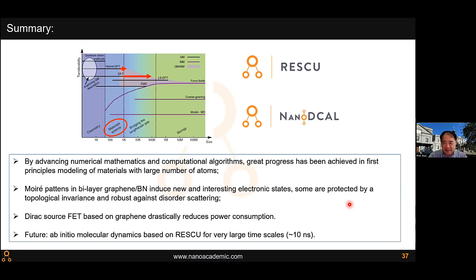But for interconnect, for many years I worked with SRC, Semiconductor Research Corporation, on interconnect. These are interconnect wires, and that's a very major problem for metal wires. Intel actually changed their process recently from copper. Many years ago, it was aluminum. What I worked on are copper nanowires. When these wires go down to 42 nanometers in diameter, the resistivity increases by a factor of two. And then that kills you.